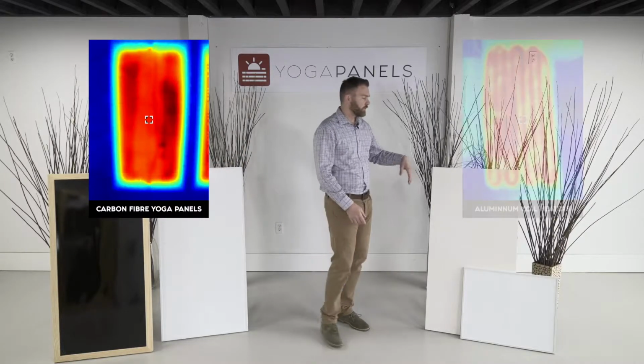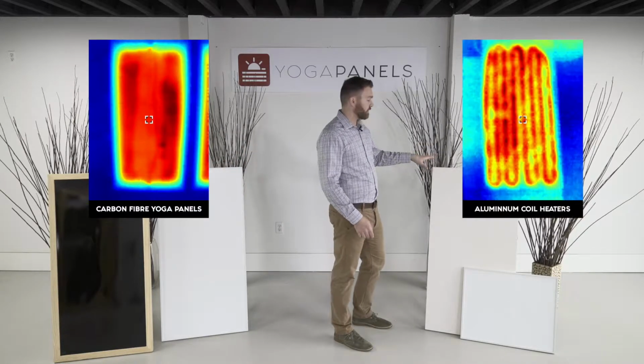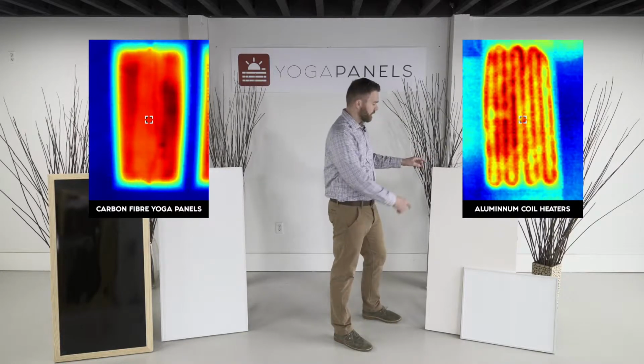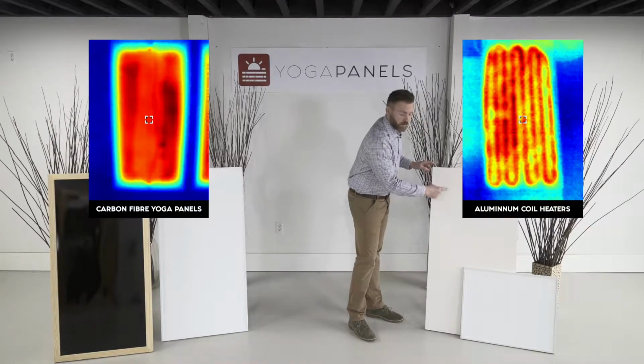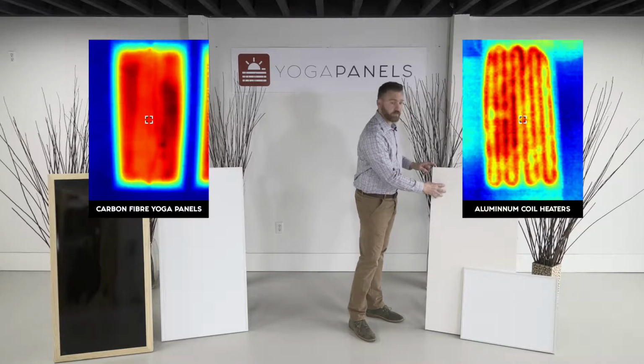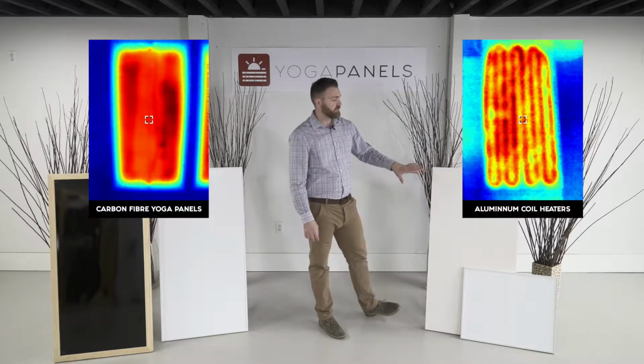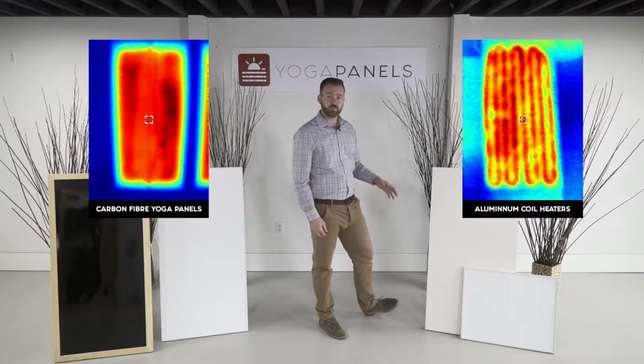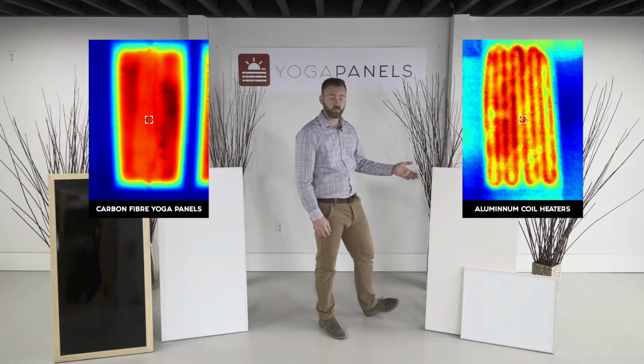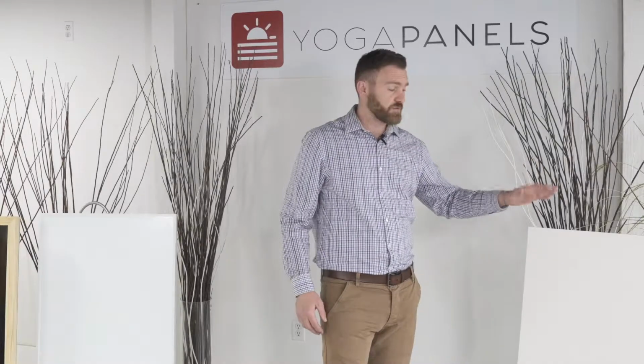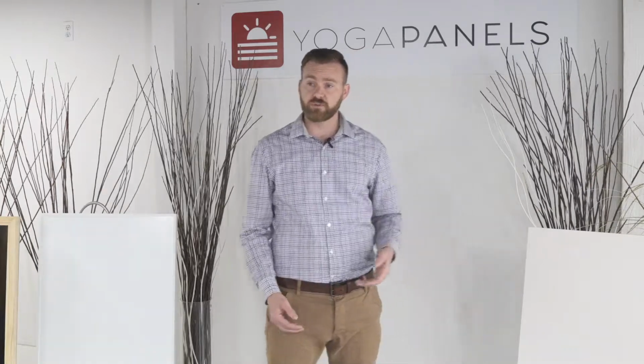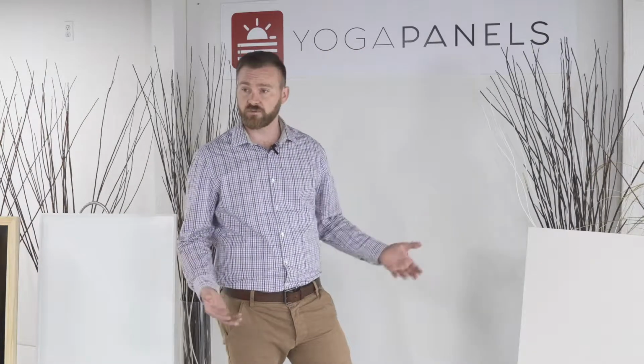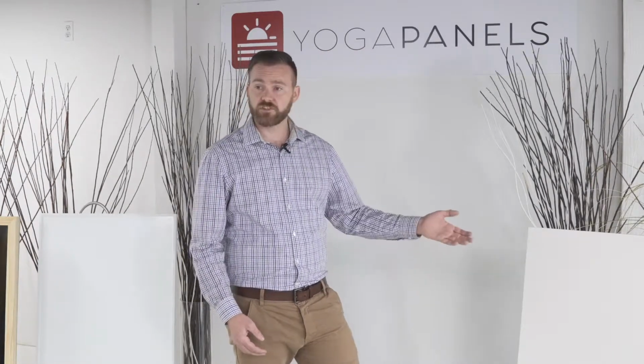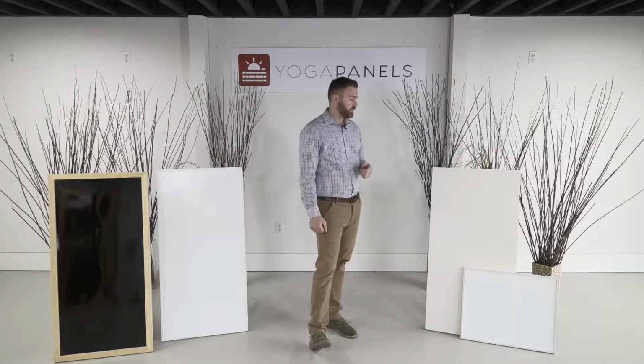When we look at the infrared panels under an infrared camera, you'll see lines that are hot. The lines will be red and then they'll be yellow on the outsides. That's because this panel is only producing 60 to 70% of its infrared in the correct range. And while it's only producing 60 to 70% correct infrared, it's also only producing 60 to 70% surface heat. So you're getting an inefficient heat and getting an improper infrared wavelength.